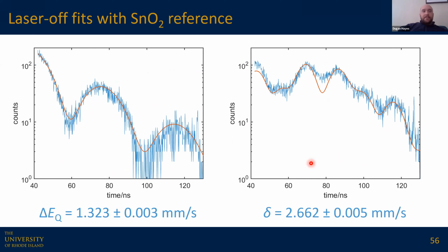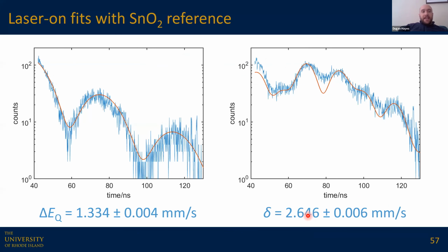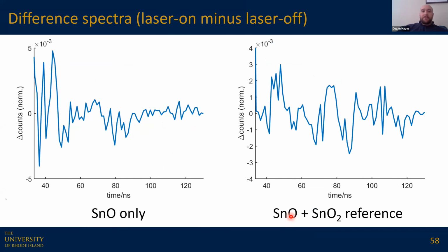So now we can take our laser off, with and without the reference, fit this using the CONUSS software to get the quadrupole splitting and isomer shift, and then do it again with laser on. We can see that we do indeed see differences that are statistically significant and greater than what we'd expect from thermal effects alone. So these are the difference spectra.